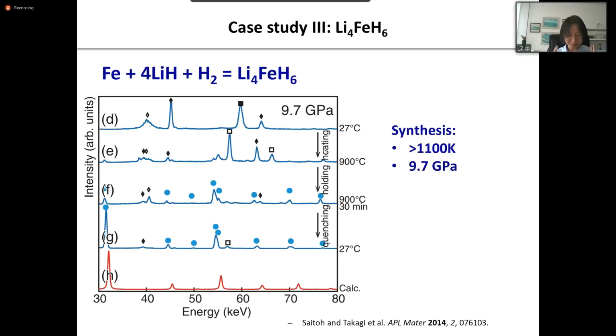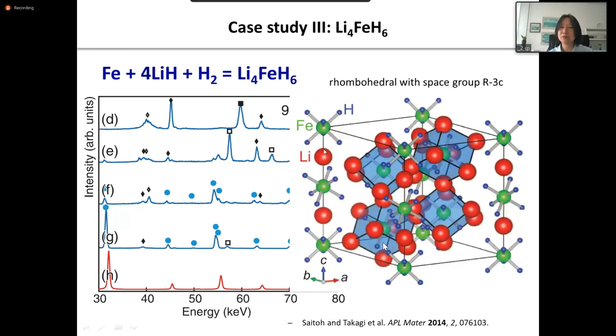This system is very interesting because if you look at the bulk phase synthesis, this is from Professor Orimo's group from Japan, and they synthesize this material under ultra high pressure. If you look at the X-ray pattern, you will see that at 900 degrees Celsius and at 9.7 gigapascal, we can have this lithium-iron hydride formed. So this is very, very difficult. And we look at this structure, we have 6 hydrogen coordinated with iron, and we have lithium in the lattice.